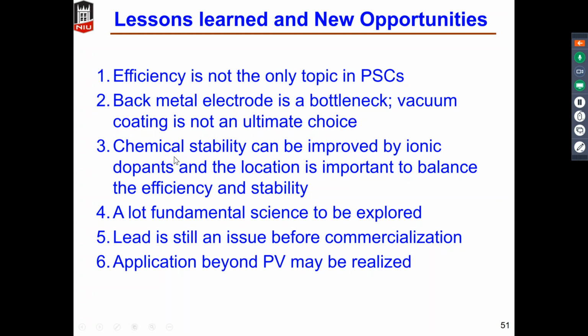And the chemical stability of perovskite materials can be improved by ionic dopants. But the lesson we learned is that the location is very important. You have to find the right location. Right now, we believe that the cap layer is the best location for such doping, in order to balance the efficiency and the stability.